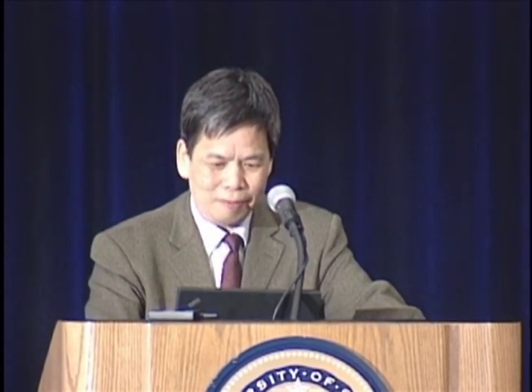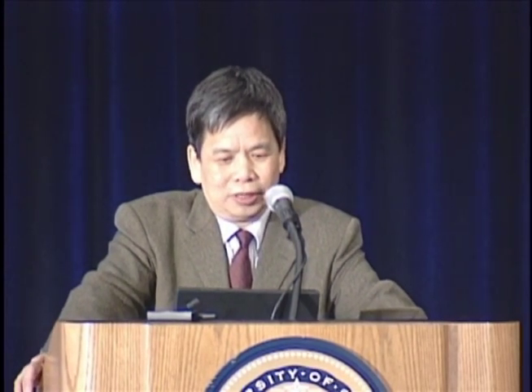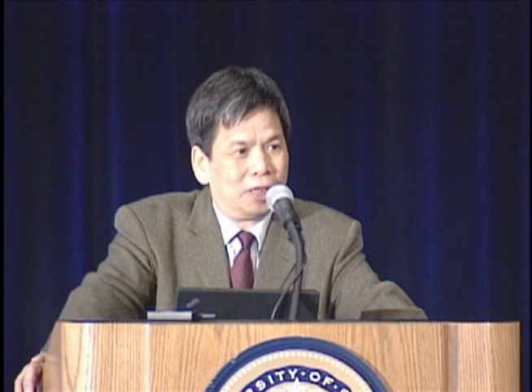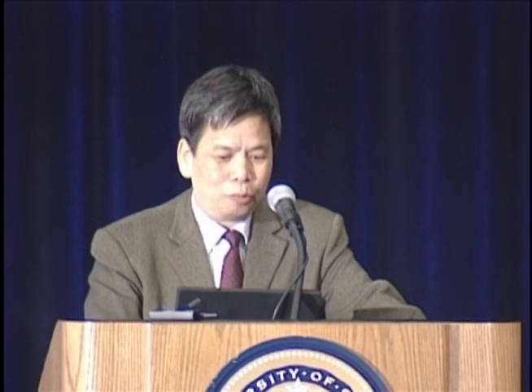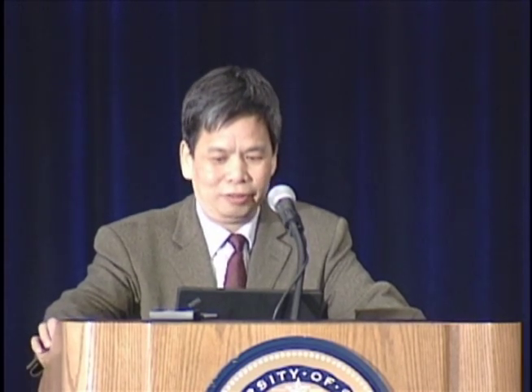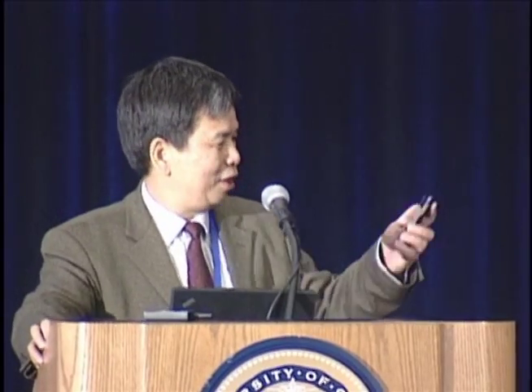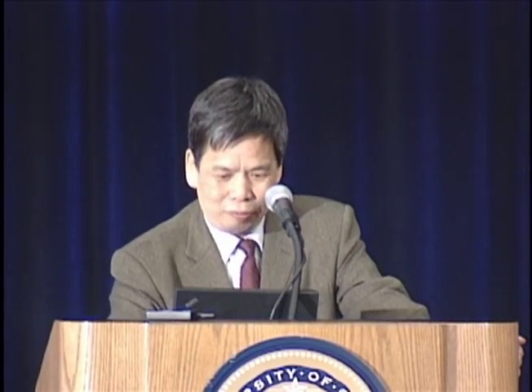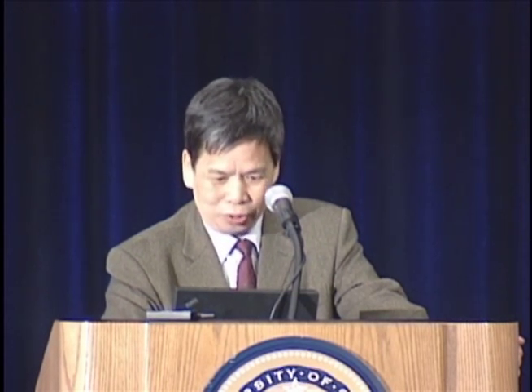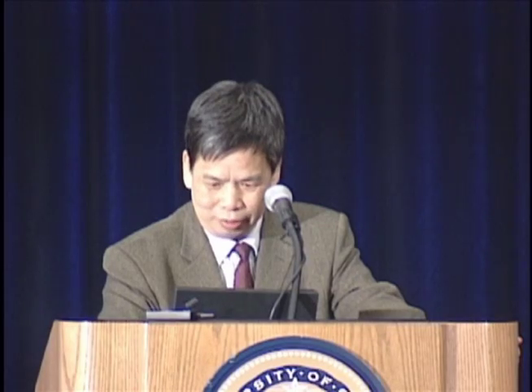And I skipped this one. Also, carbon nanotube thin film is transparent, and transmission is around 90%. And we use it to make a touch panel. This touch panel replaces indium tin oxide, which is commonly used nowadays for commercial touch panels. I have a first carbon nanotube touch panel sample. This is the first mobile phone using our carbon nanotube sample. And we have a mass production line for this carbon nanotube touch panel.